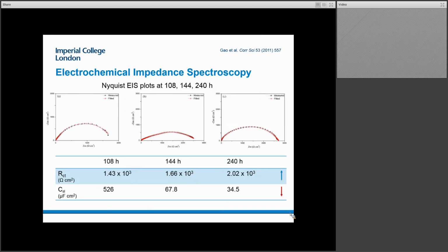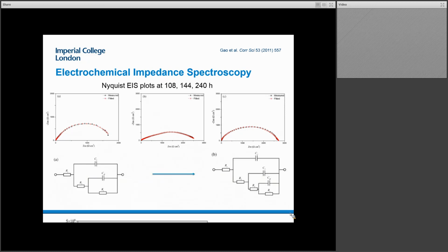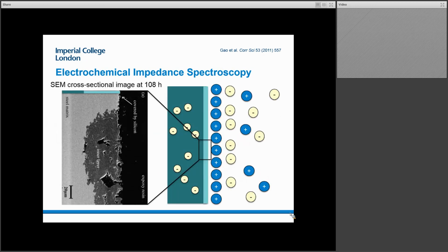But the more exciting thing that the authors are drawn to is the fact that it's back to this issue of charge transfer. And so they believe that, in fact, this significant increase in the resistance to charge transfer is likely related to the fact that that new layer is actually changing in form, perhaps becoming less porous. And so that's where this, again, becomes quite intriguing. So we've moved and we've hypothesized how the layers are changing. We've got an idea, and what's very nice in this particular example is that we are now going to take electrochemistry out and put it with other types of data and analysis.